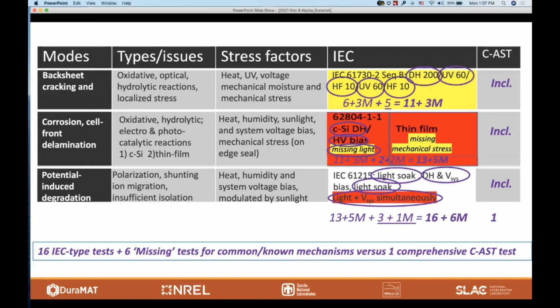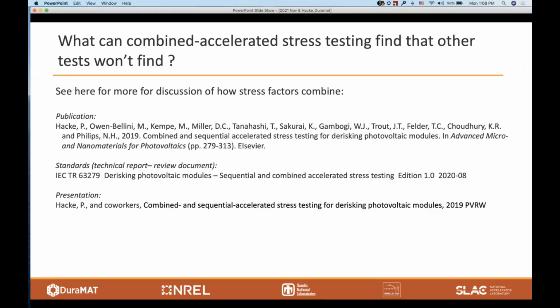Corrosion, cell front delamination: there are a number of tests out there, some existing, some missing. And potential induced degradation: we're just getting that finally standardized in the last couple of years. But they're still missing the factor of light and voltage simultaneously to understand if it's really going to happen. So if we add it all up, you have to do 16 IEC type tests, plus there are 6 missing tests, that's to say not standardized or in the process of being standardized for the common known mechanisms, versus one comprehensive combined accelerated stress test. You can find more in the literature about how stress factors combine and why it's necessary to do that. We have three different items here: a publication, a technical report, which is basically a review document, and this presentation in the 2019 PVRW does a pretty good job of explaining what I just showed in more detail.